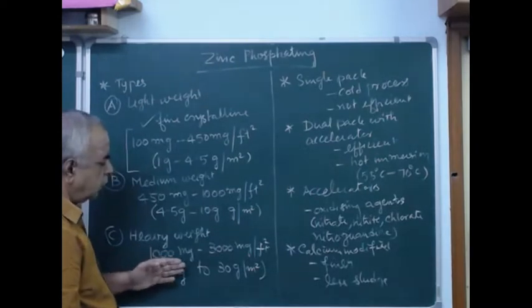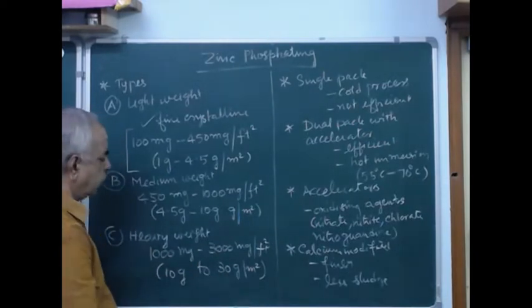Here, 1000 to 3000 milligrams per square foot, that is 10 to 30 grams per square meter.